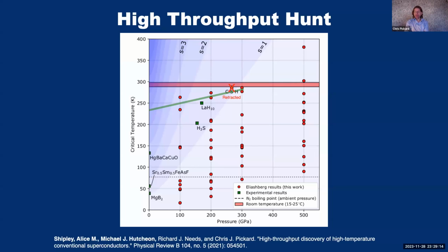Now, the most striking thing for me about this result was that as we lowered the pressure, the maximum superconducting temperature that we found was certainly decreasing a bit, but it wasn't decreasing very rapidly. So this suggested to me, and probably to others as well, that it really might be worth looking at lower pressures, down to ambient conditions, to see whether there are any candidate structures that might be superconducting in this range above 50 Kelvin or so, which would then surpass magnesium diboride as the highest Tc conventional superconductors.